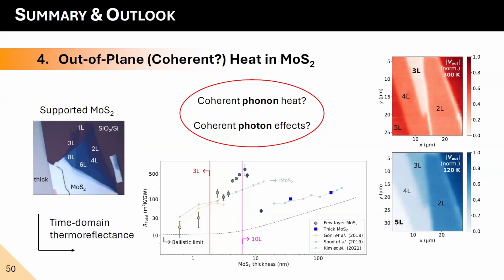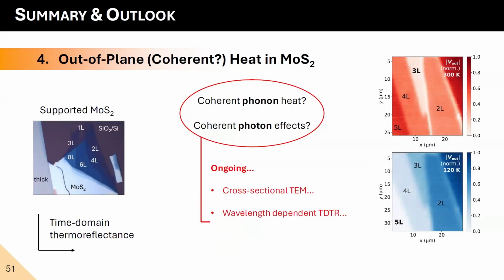Actually, to unravel these two potential contributions, we are performing cross-sectional transmission electron microscopy measurements to look at the quality of our interfaces, and also we are performing probe wavelength dependent TDTR measurements, which would allow us to observe whether it's coherent photon effects that we're seeing.